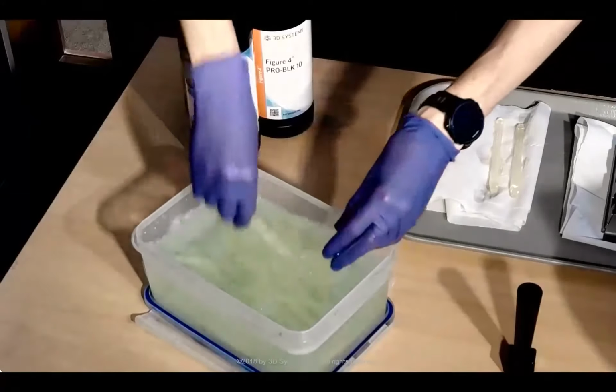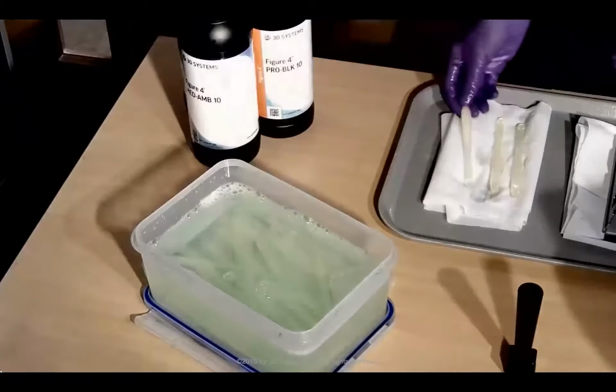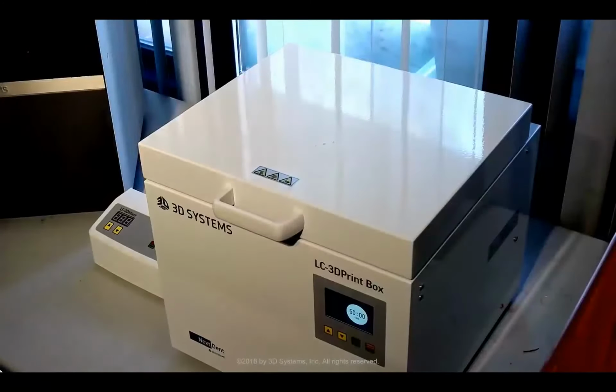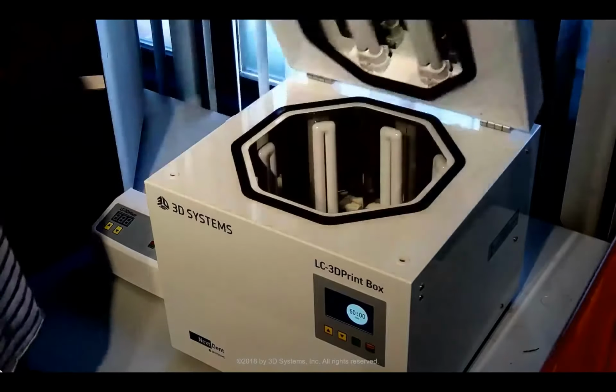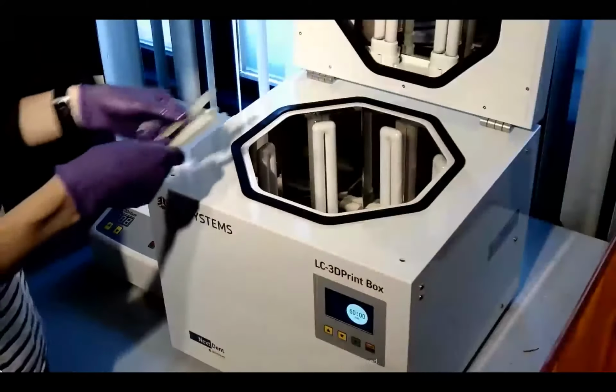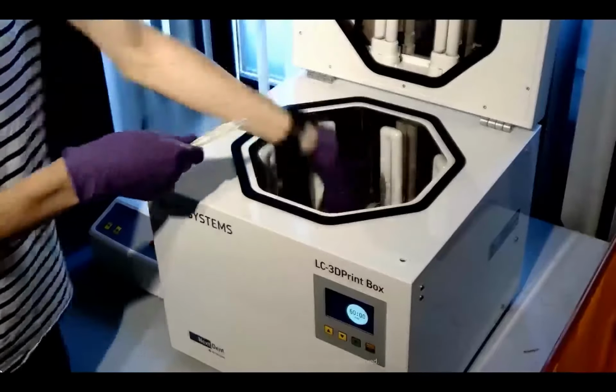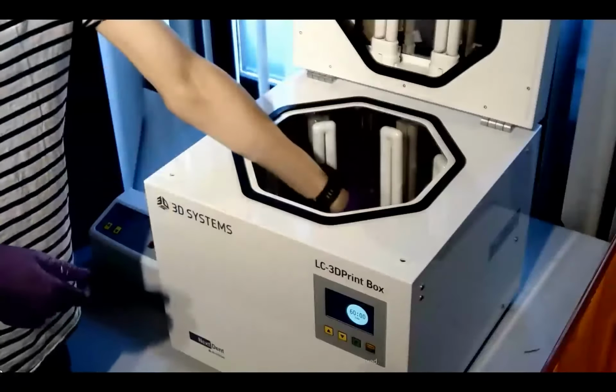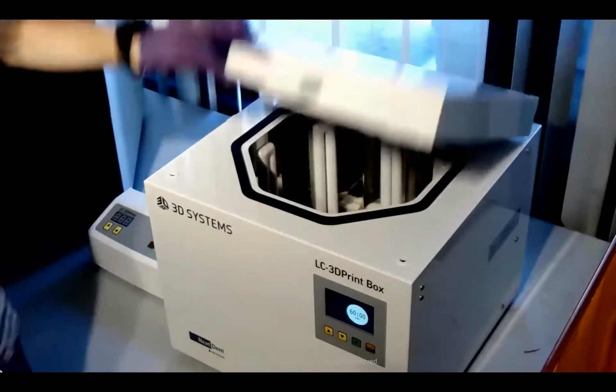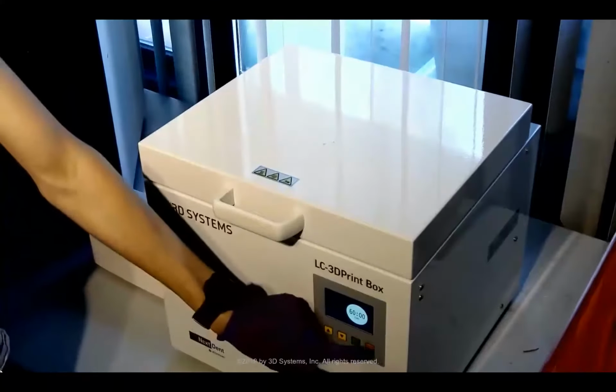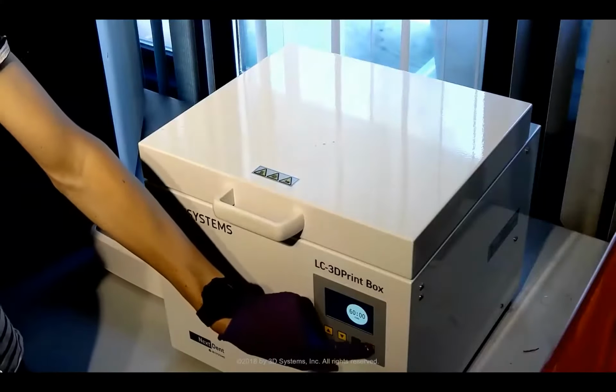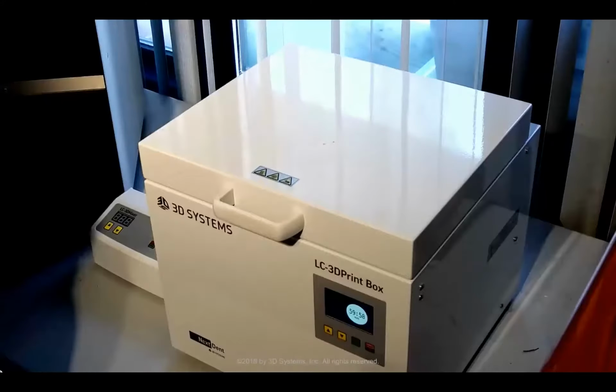So as you can see, we leave them to dry after this process. So we dry them off and then we can put them into the UV tank. The UV tank is used to post-cure the parts. We call them green as they come off the machine because they need an additional amount of UV light to get the full material properties from them. So we cure them at different amounts depending on the different materials.